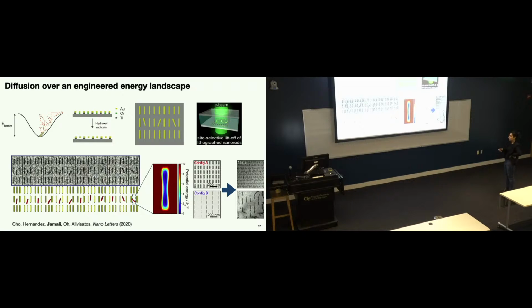Then we can study the interaction of these mobile nanorods with the fixed array of nanorods around it, and go back to the theories that explain the interaction of one single nanorod in a fixed energy landscape with certain charge density and Debye screening length, and back-calculate those interaction parameters. So basically, what is the Debye screening length, what is the charge density. Once we have those values, we can go back to the nanofabrication room and make these rods in certain forms that we want.